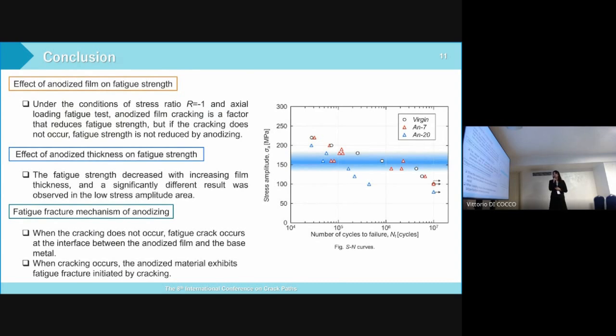Finally, this is the conclusion of our study. First, regarding the effect of anodized film on fatigue strength: under the conditions of stress ratio equal to -1 and axial loading fatigue test, the cracking of the anodized film is a factor that reduces fatigue strength. But if the cracking does not occur, the fatigue strength is not reduced by anodizing. Next, regarding the effect of anodized thickness on fatigue strength: the fatigue strength decreased with increasing film thickness, and a significantly different result was observed in the low stress amplitude range.